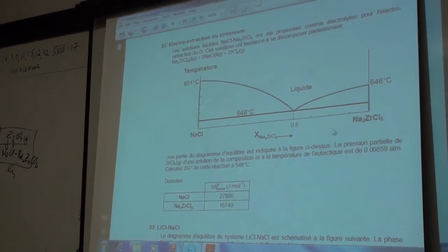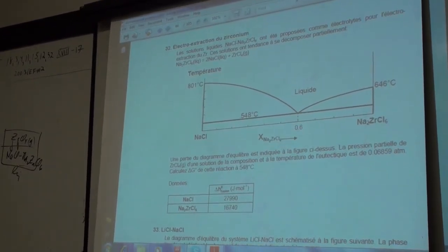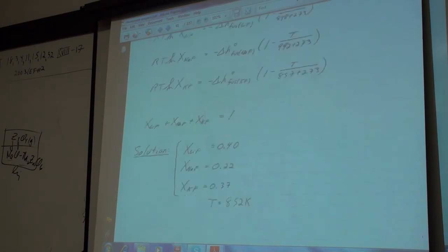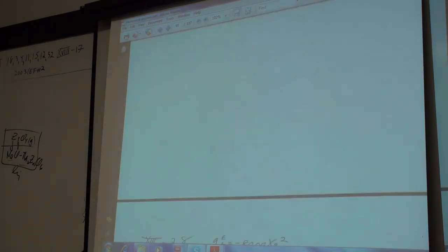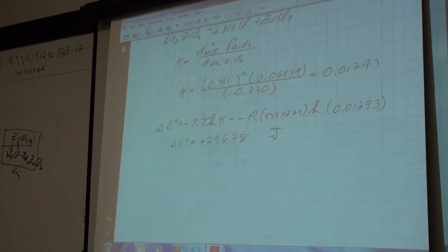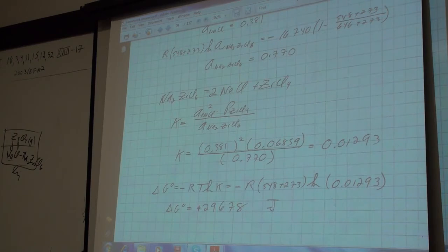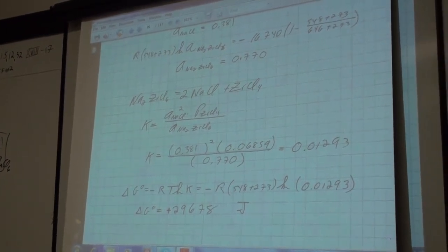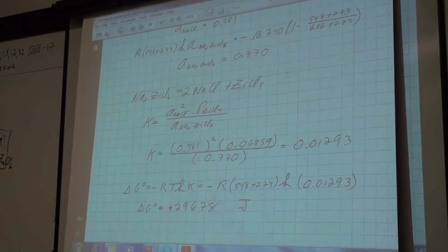All right, so at that point, in other words. Okay, so this is the reaction that we're interested in, the equilibrium between the 2 salts that are in the 2 components of this liquid phase and the gas phase. And the equilibrium constant then is equal to the activity squared of sodium chloride times the partial pressure divided by the activity. The partial pressure has been measured, so in order to get the equilibrium constant, from the equilibrium constant, of course, you get delta G naught equals minus RT log K. So to get the Gibbs energy, the delta G standard of that reaction, you need the equilibrium constant from this equation.